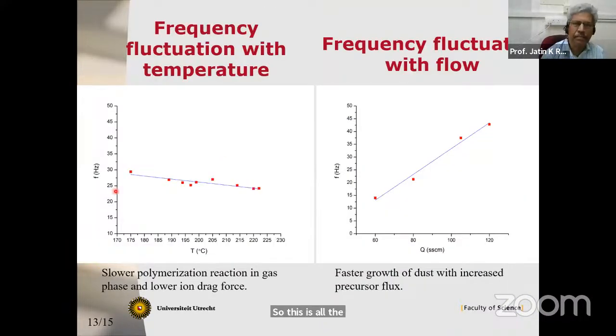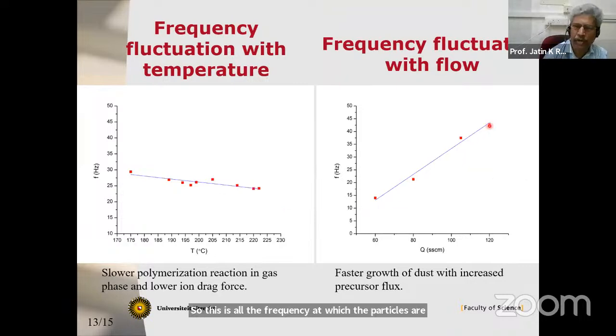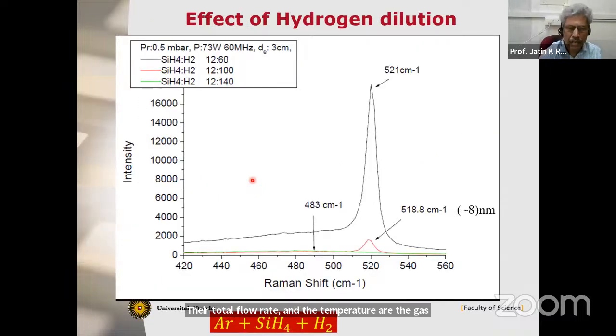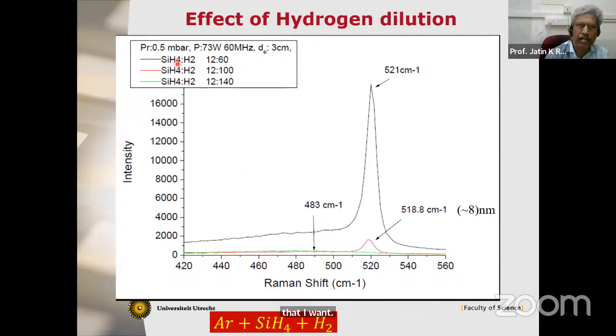This frequency basically depends on two things, the total flow rate and the gas temperature. This has been well documented by us. Now, one more thing: if I use only silane, without hydrogen, in the gas phase, I get big particles. But if the hydrogen concentration goes up, you can see the particle size comes down and down. This is a very big size. We don't want that. It has to be smaller than 5 nanometers. So you go somewhere above this, with more hydrogen, then you get small size particles.